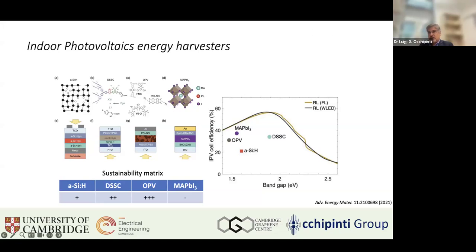So that's for DSSC. Also in terms of the OPV, organic photovoltaic, these are also very good candidates in terms of sustainability. These are probably the most accepted green materials, if you allow me. However, typically these were based on a bulk heterojunction with fullerene-based electron acceptor. However, fullerene-based electron acceptors suffer from light-induced degradation, and also they are relatively expensive in terms of synthetic cost. So more recently, the trend has been towards non-fullerene-based acceptors with longer-term stability to light exposure, but slightly higher production cost as well. So there is a balance between environmental sustainability and economic sustainability on the other side.